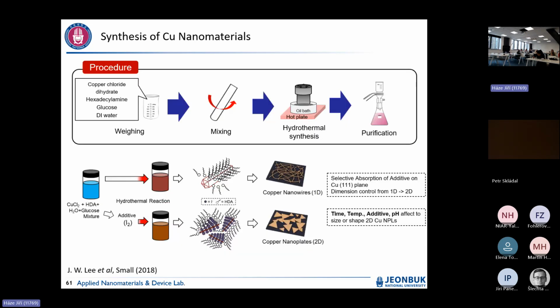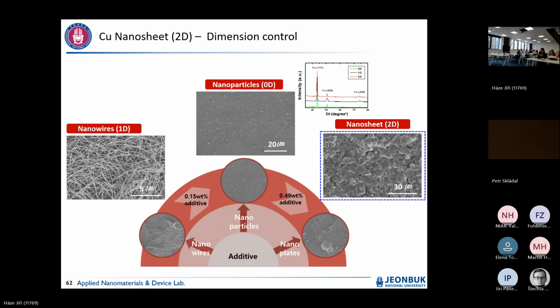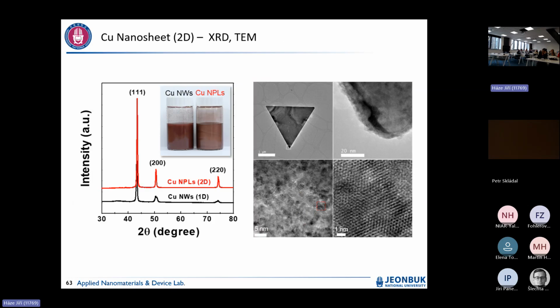And the synthesis is really easy because I usually use DI water as the solvent. We just put everything in the reactor. It is hydrothermal, or sometimes called an autoclave, right? Then we can leave our mixture in the oven, heated up to 100 Celsius. This is the final product. We can now control 1 dimension, 0 dimension and 2 dimension. We can control everything. So this is the image. This is the old one. I'm going to skip this one.